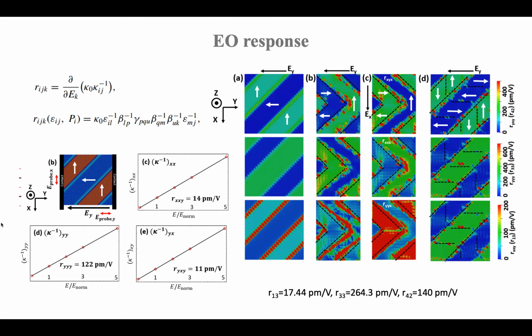The good news, qualitatively, it works. The bad news, the one I'm really interested in, which is R42, is way, way underestimated. It's supposed to be 1,000. It's coming to like 140. But qualitatively, we can do that. The most important message from this study was that if you start with different microstructure, your Pockels tensor changes locally. And so you need to know what kind of a field you have to predict the electro-optical response.